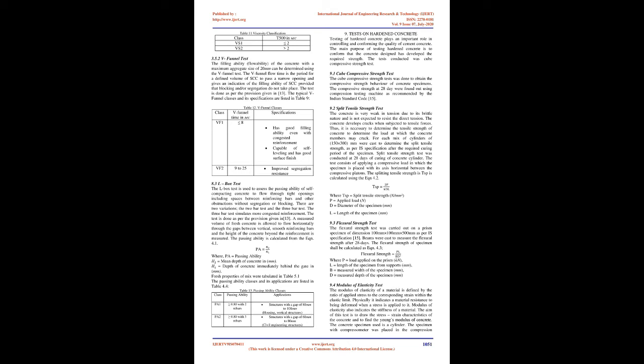3.5.2 V-funnel test. The filling ability, flowability, of the concrete with a maximum aggregate size of 20 mm can be determined using the V-funnel test. The V-funnel flow time is the period for a defined volume of SCC to pass a narrow opening and gives an indication of the filling ability of SCC, provided that blocking and/or segregation do not take place. The test is done as per the provisions given. The typical V-funnel classes and their specifications are listed in Table 9.